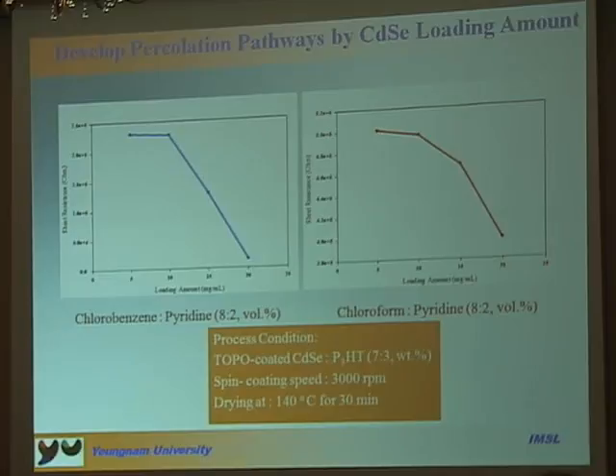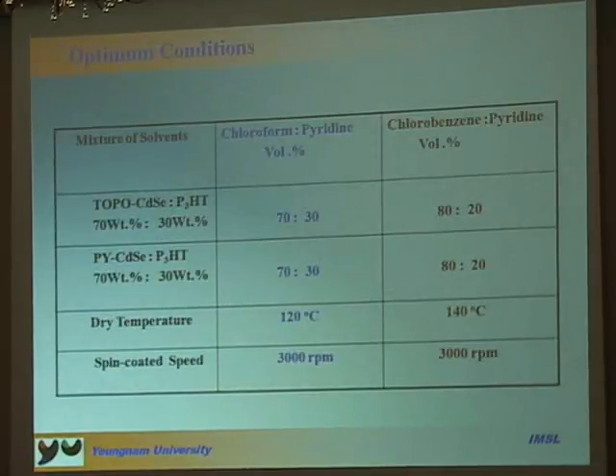In this data, if we increase the loading amount to more than 50 milligram, we can say the resistance of the CdSe system decreases. That means the percolation pathway was developed. We can see that in the case of chlorobenzene and chloroform, we get the same curve. So after investigation in this objective, we get the optimum condition for the loading.